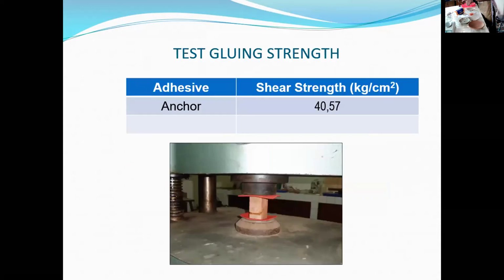We wait for the adhesive that we cook to be more thick. We also run some tests, strength test. Because we have the equipment to test the shear strength, that's what we did. We test the adhesive strength using anchor, with a pressure of 40.57 kilogram per centimeter square. This material is strong enough once it's dried.